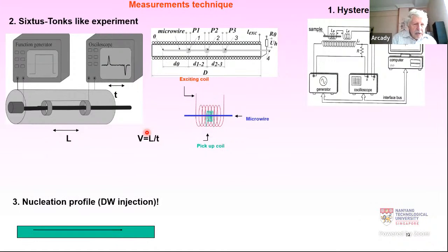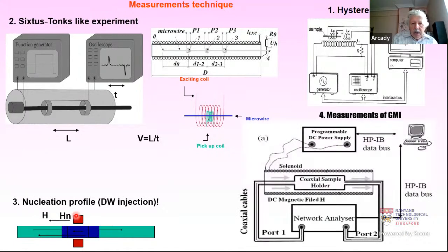Also, an important technique which we realized in our laboratory: we can nucleate, inject and roll domain walls in different parts of microwires of our sample by a local magnetizing coil, and then we can measure the so-called nucleation profile on our samples. And for the giant magnetoimpedance effect, we employ the so-called coaxial method with a sample holder, which allows us to measure the magnetoimpedance effect over a quite broad range of frequencies.